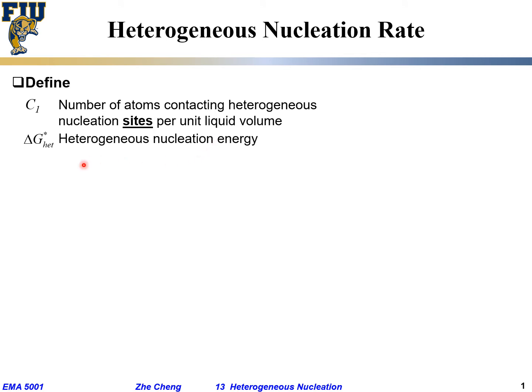And then ΔG*, what is that? G hetero star, that's your heterogeneous critical nucleation energy, which is only a factor of the homogeneous one. And f1 is still the frequency of adding an atom to the heterogeneous nucleus. f1 is the frequency of adding atom.